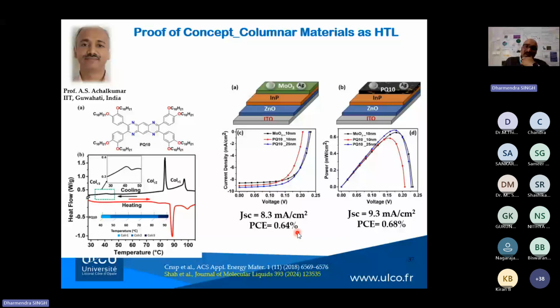Then, to prove our concept, we replaced this MoO3 layer with the PQ10 material, and we kept the other structure the same. The JSC was found to be 9.3 mA per centimeter square, and PCE increased to 0.68%. So this was the first proof of concept that these columnar materials can be used as HTL, and can also be used at the interface in order to improve the efficiency of the material.